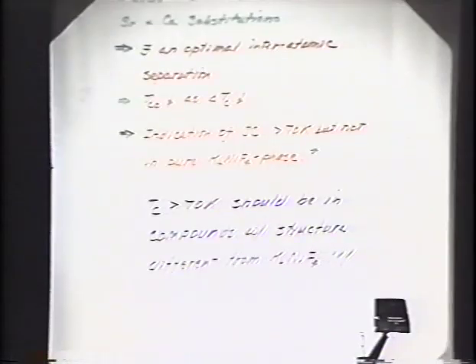Let me just show you this curve, the original curve measured on November the 25th. You see the resistance drops all the way, starting from 70 degrees to 50 degrees, and this was mentioned in our first paper. And then we continued on. We decided that for TC higher than 70 degrees, we should go into compounds with structure different from K2NiF4.